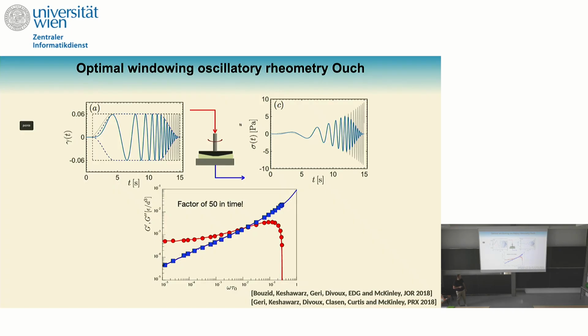So here I'm showing the curves from simulation, G prime and G double prime. The points correspond to the discrete method where you do a sinusoidal oscillation, you stop, you change your frequency, another oscillation, stop, change your frequency, and so on and so forth. But if you send this signal that is modulated in frequency, this is the line that you get here. And you see in one simulation or one experiment, you get the full spectrum.